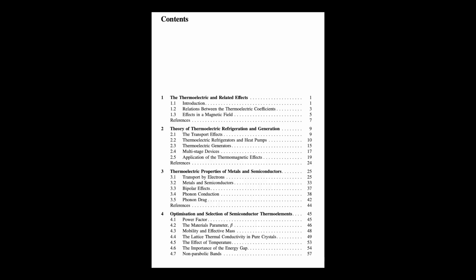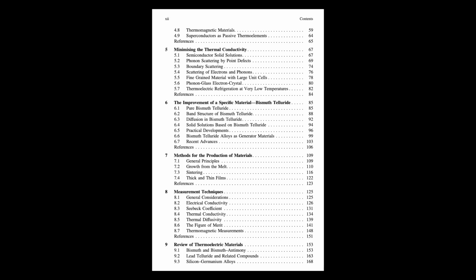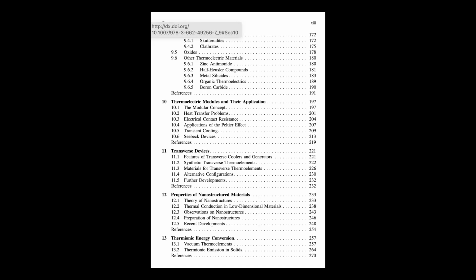What about using fine grains and large unit cells in the crystal structure? How does that combo work? Materials with large, complex unit cells, the basic repeating block of the crystal, tend to have more complicated vibration patterns. More optical modes, in addition to the main heat-carrying acoustic modes. These optical modes are usually slower, don't carry heat as well. Now, if you make such a material fine-grained, the grain boundaries scatter the main heat carriers, acoustic phonons, because the inherent vibration physics is already complex in large unit cells. Comparing fine-grained versus large-grained versions of the same material often gives more insight than simple scattering models.